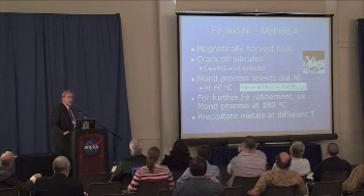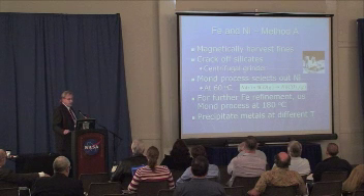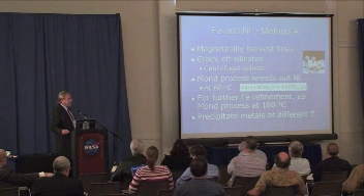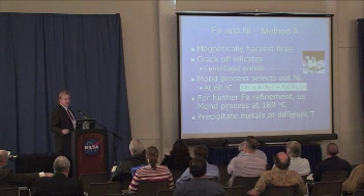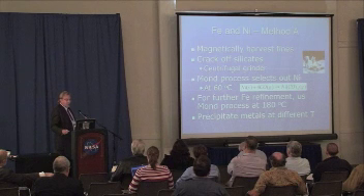So there are 2 ways to get iron and nickel out of lunar soil. There's more than that, of course, but the 2 that we studied. The first was to magnetically harvest fines. These fines are left over from iron and nickel meteorites that hit the surface. They're often associated with silicates, clustered on those, so we crack those off with a grinder.